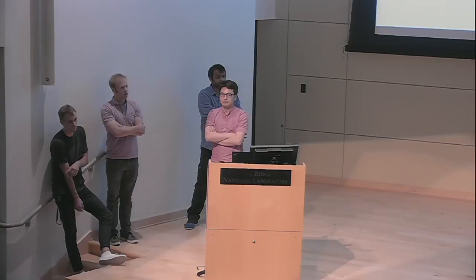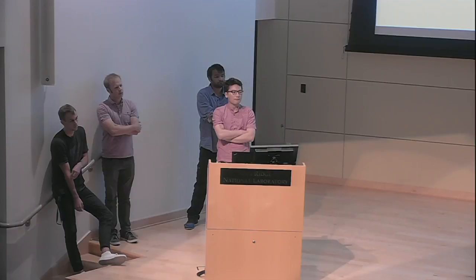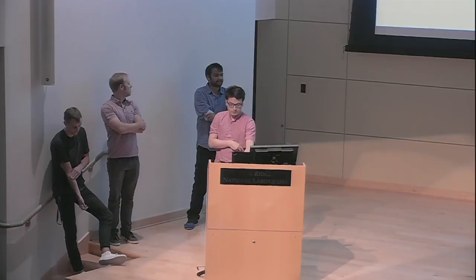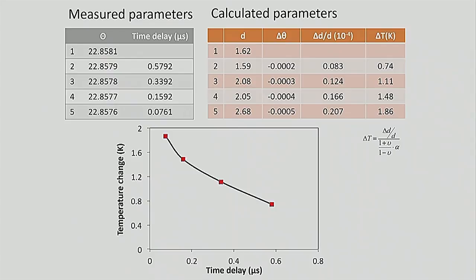Could you measure thermal conductivity by just checking how the temperature evolves? Yeah. So how the temperature evolves and if you know your system geometry, you can do a simple mathematical model that gives you heat flow through your model and you can back out thermal conductivity if you can measure your temperature. What if when you have the x-ray beam hitting where the laser hit, what if you had it not where it hits, but on the back side of the sample or off to the side? You won't see the effect of the thermal conductivity? You won't get the effect of the pulse. And these are localized effects. So what we are assuming is that your system responds only to that pulse. So if anything is far out from it, it practically doesn't see it. And these are very mild pulses. So we are like one millijoule per centimeter squared, so it's like very mild pulses. So he does not know if I am getting hit by a pulse basically. Okay, but I've heard of experiments where they do shock waves, take a silicon wafer and hit one side and then you have the back side. Shock waves will propagate through your material. I don't think heat will do. And once again, these are very mild pulses.